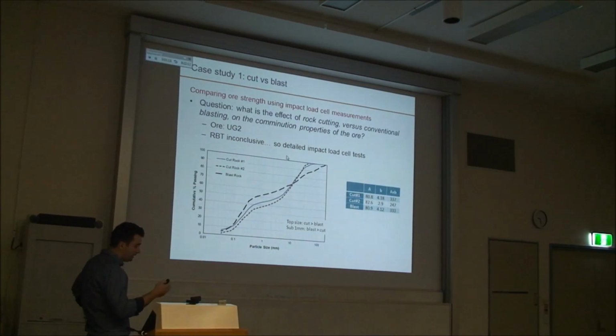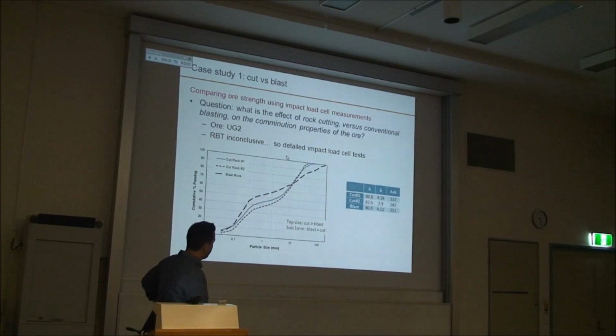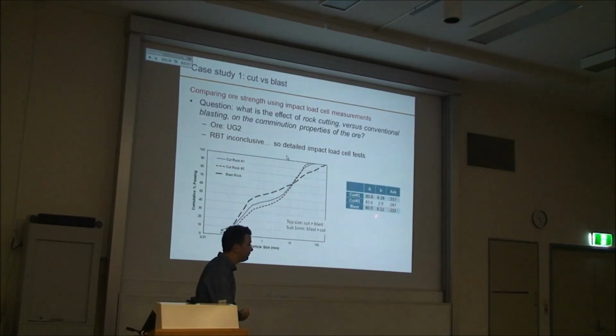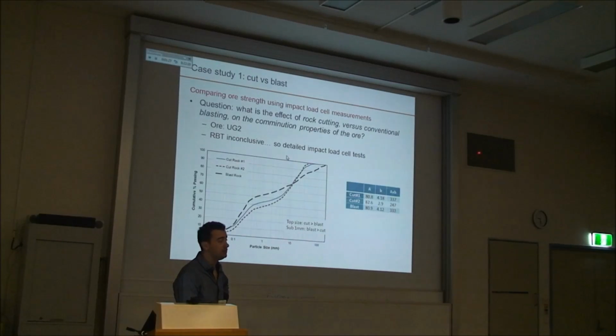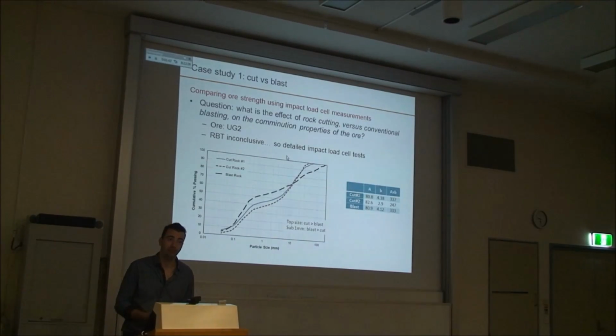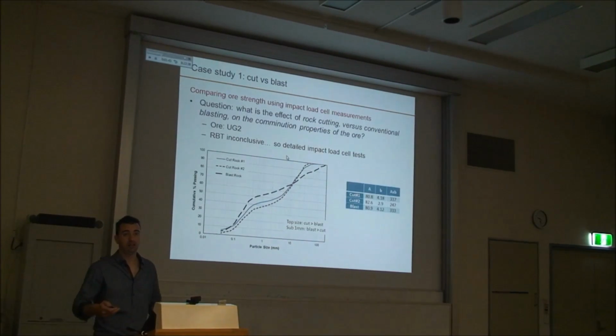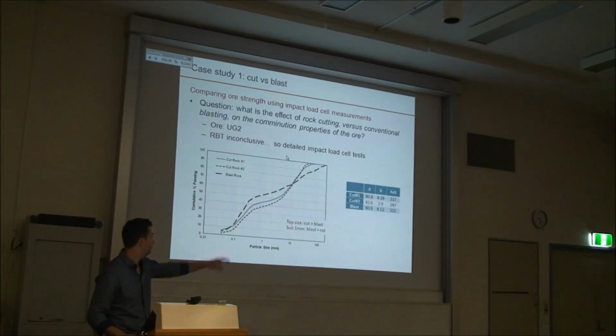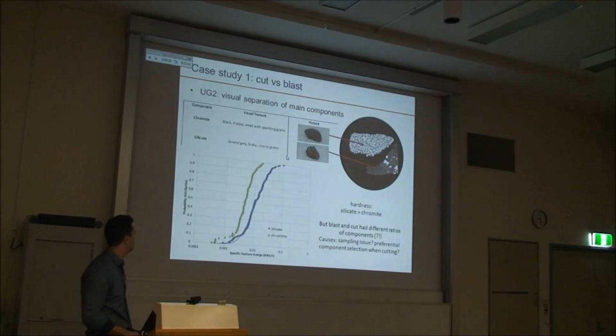So we did the A times b with the rotary breakage tester, and these are the A times b values we found. Because this is UG2, a nasty ore, the values are really high. This is because of the chromite particles. The chromite agglomerates are quite soft and they break preferentially, quite easily. So I said, well, the numbers are all over the place and I can't really compare them. So I went on and carried out the impact load cell tests to look at the properties and get away from those numbers.